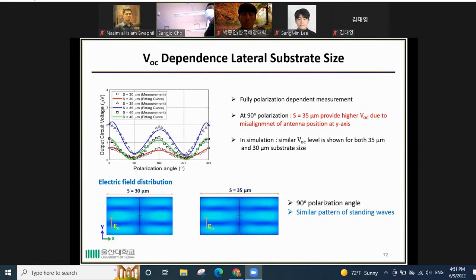And this is the full polarization dependent measurement for 3 cases of the substrate size: 30, 35, and 40. From this, we can see at 90 degree polarization, the 35 substrate size provides a higher VOC because of the misalignment of the antenna position in the y-axis. However, in the simulation, we verified that the VOC level should be the same for 35, 30, and also 40. To prove that, we also check the electric field distribution for 30 micrometer and 35 micrometer substrate size with 90 degree polarization angle, where the electric field direction is perpendicular to the antenna axis. And you can see that similar patterns of the standing wave happen for both cases. So that's why the output voltage is the same.